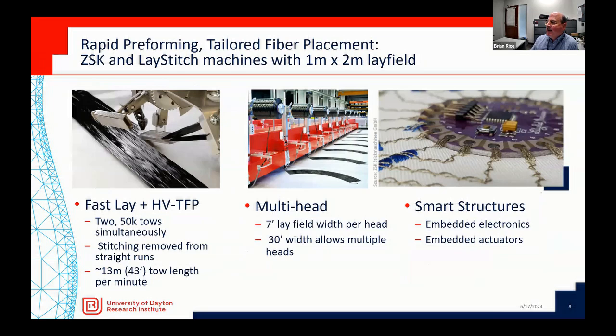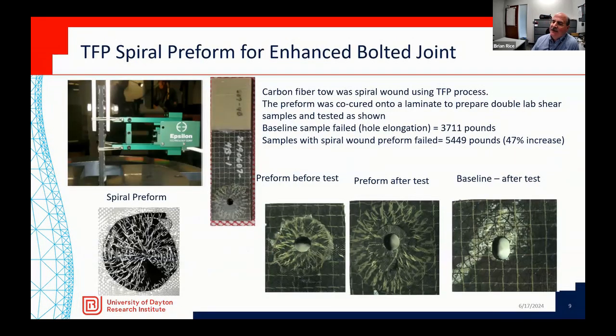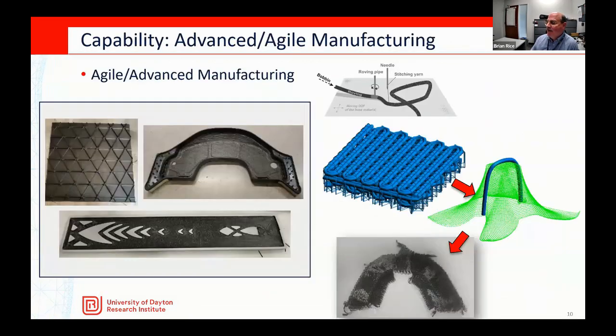And tailored fiber placement, here in the US, is not heavily used, but in Europe, it's actually been around for over a decade in production parts, such as the Airbus A350 window frames, for example. One IACMI project we did was, can we enhance the bearing strength of a hole in a composite, if you're doing attachment hardware and so forth. So basically, you're making this little spiral reinforcement that weighs about 1 gram, but by just adding that gram's worth of composite, you got about a 47% increase in the load, from 3,700 pounds to 5,400. So it's pretty significant improvements possible there.